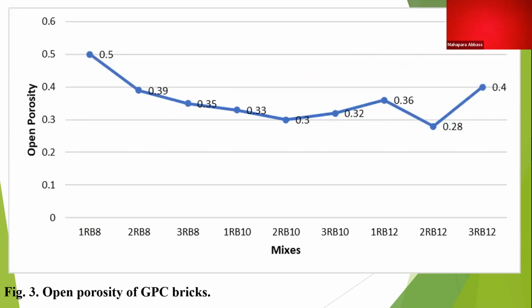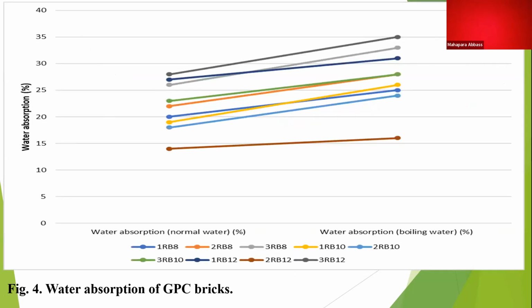Open porosity was measured to know the quantity of pores in the mixes. What we have seen is that the quantity of pores in mix 2Rb12 was lesser than in all the mixes, and in the control mix and in the mix with silica to alumina ratio 1 and sodium hydroxide molarity 8, the quantity of pores was maximum, at 0.5. Then a water absorption test was done, and here also the water absorption by mix 2Rb12 was lesser as compared to all the mixes, and was greater in mix 1Rb12 and 3Rb12 as compared to all the mixes.